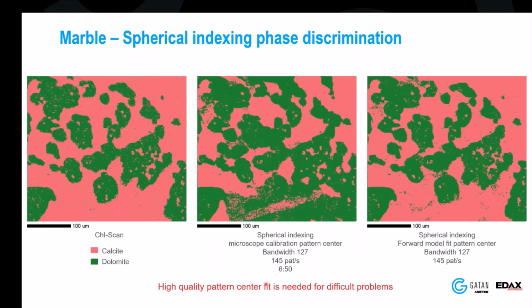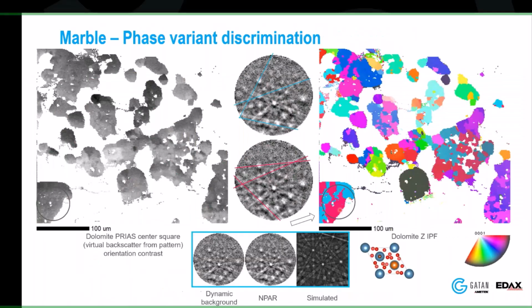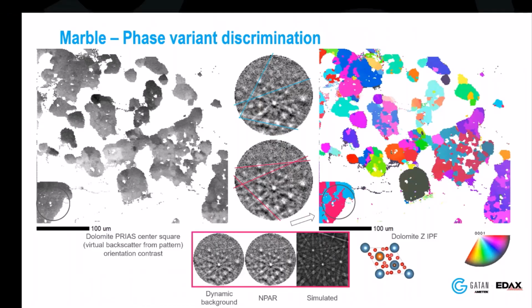Now, of course, having a better pattern center fit is good, but we've built an algorithm for that, which helps us get a little bit more differentiation on some things. But in the end, when we do all of our tricks that we have available to us, I can start to see some pretty major differences in that data set that we just collected. So here I've pulled out just the dolomite information, and this is going to be a royal we, because this data was collected by my colleague Renee Declos over in Europe. Most of the data is actually collected by Renee, so big shout out to Renee for doing most of the heavy lifting on this presentation. Now here, there's a big grain down here that was speckled in the previous map.